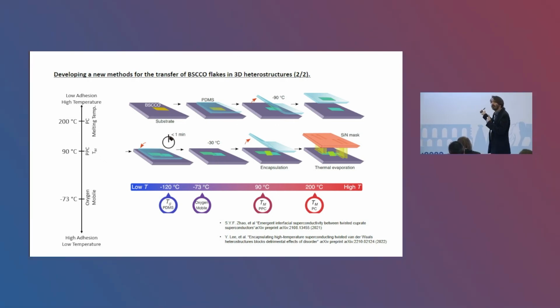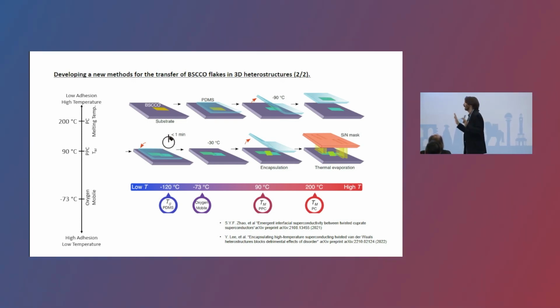But if you do that with the BSCCO, you will devastate your system, without mentioning that for this method you have to use solvent, and solvent contains water, so you are going to devastate your system twice. So you really cannot do any of this. We know the oxygens are mobile above minus 70 degrees Celsius, so it turns out that if you exfoliate the BSCCO flake with the PDMS, and the PDMS goes very close to its glass transition temperature without overcoming it, it becomes like a Scotch tape, really a Scotch tape. It becomes incredibly sticky. So then what you can do is restack this system on top of each other and give a twist. This is impossible otherwise.